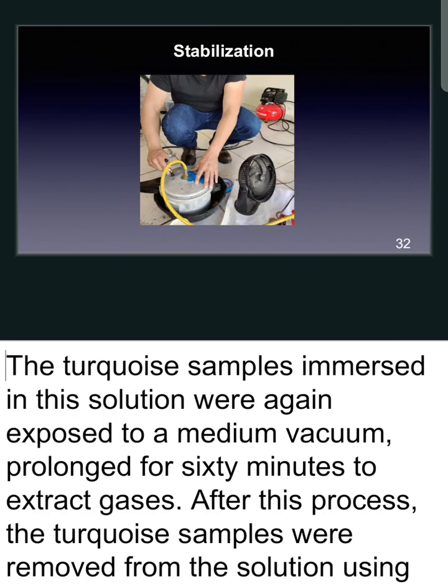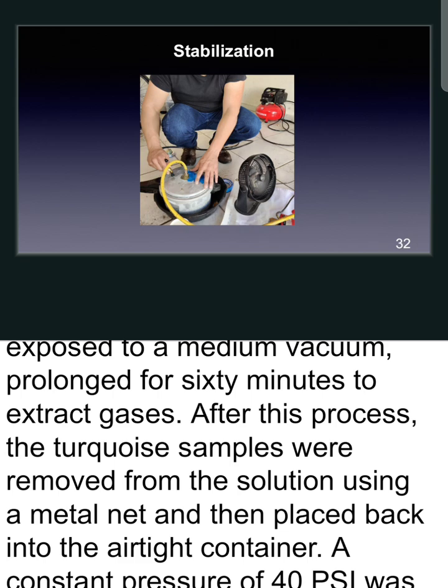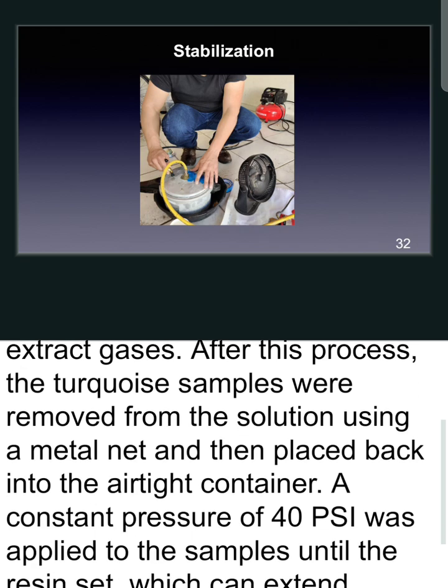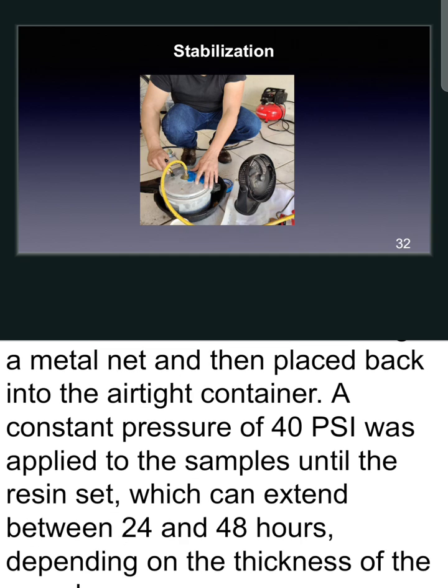Then, after having the turquoise samples immersed in the solution, they were again exposed to a medium vacuum, prolonged for 60 minutes to extract gases. After this process, the turquoise samples were removed from the solution using a metal net and then placed back into the airtight container. A constant pressure of 40 psi was applied to the samples until the resin set, which can take between 24 and 48 hours, depending on the thickness of the sample.